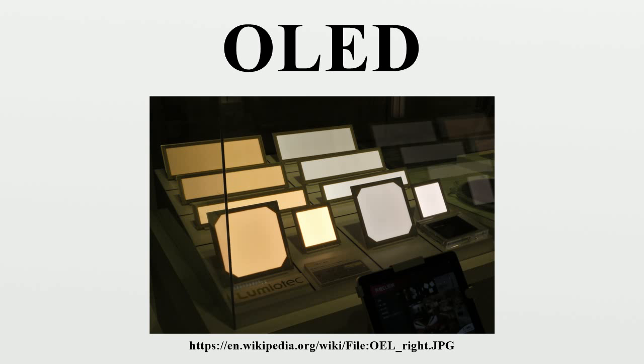Indium tin oxide is commonly used as the anode material. It is transparent to visible light and has a high work function which promotes injection of holes into the HOMO level of the organic layer. A typical conductive layer may consist of PEDOT:PSS, as the HOMO level of this material generally lies between the work function of ITO and the HOMO of other commonly used polymers, reducing the energy barriers for hole injection.